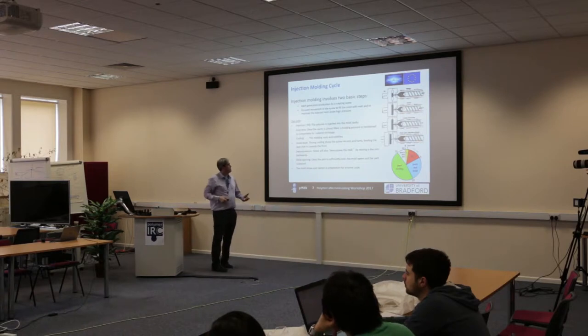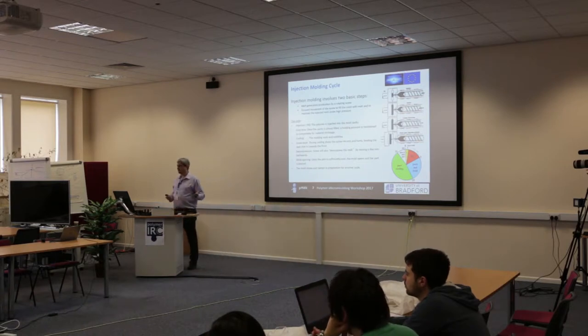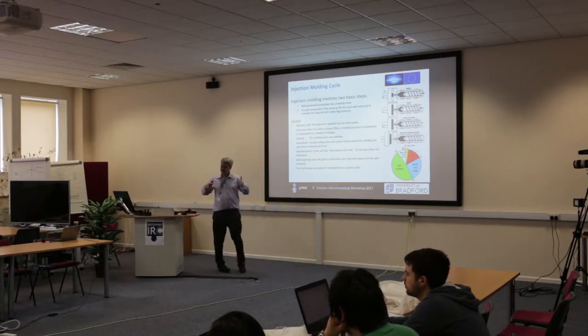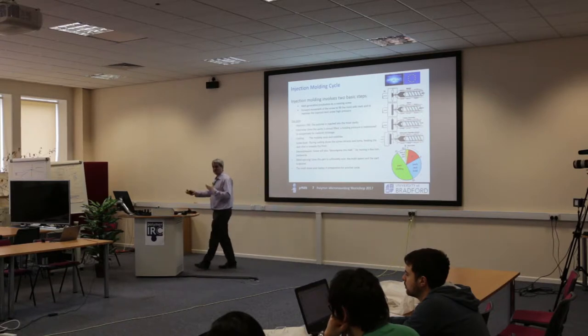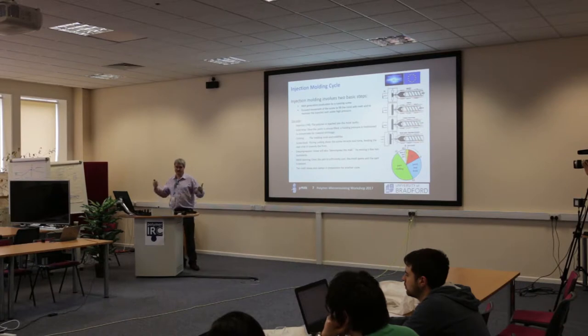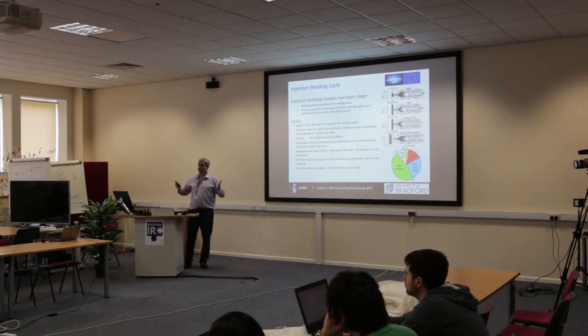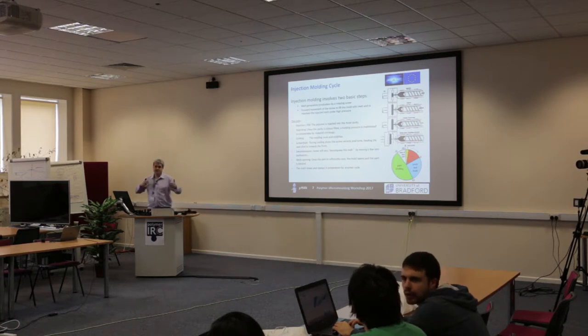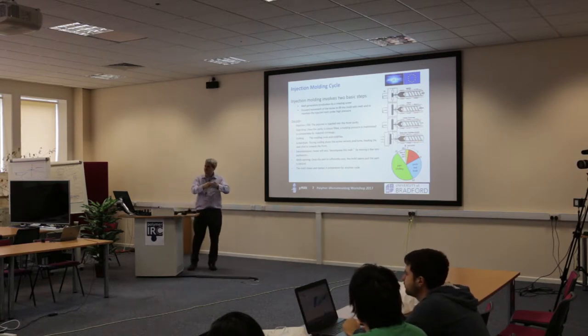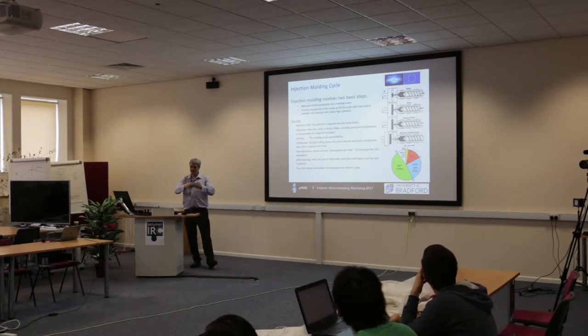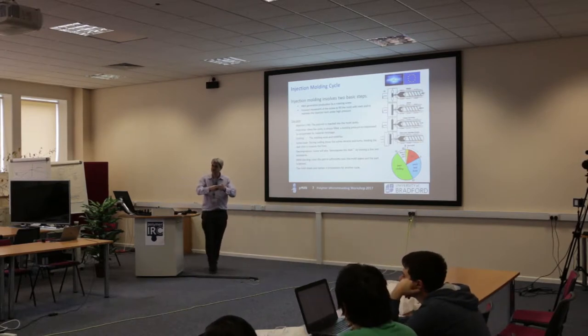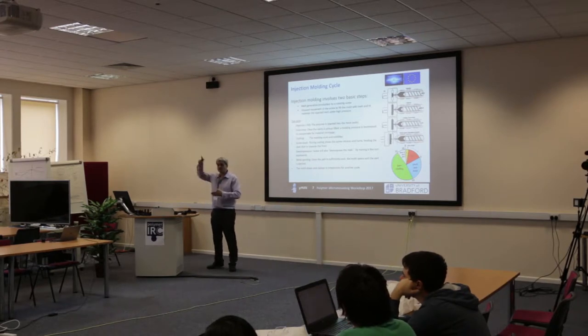The first part is the filling stage — injecting the melt into the mold cavity. The screw moves at a constant velocity, which is a machine setting that influences shear rates and the speed of cavity filling. If we stayed in constant velocity control and completely filled the mold cavity, there would be a sudden pressure spike because the material has nowhere to flow, which could damage the tool. So we actually part-fill the cavity to about 99% full, then switch the screw control from velocity-controlled to pressure-controlled.